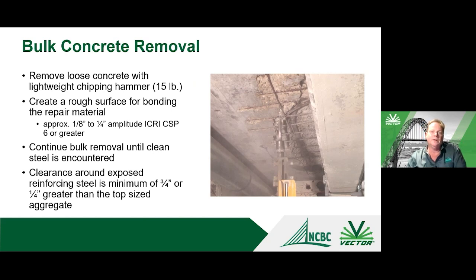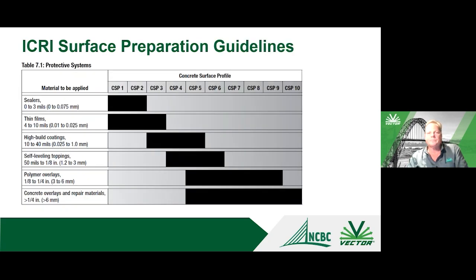of the chipping hammer can be important to remove deteriorated concrete without doing too much further damage to the base concrete or the substrate. And we want to make sure, as I mentioned before, to have a good surface profile and look at the clearance around the reinforcing steel. One good rule of thumb is if you can get a gloved hand behind the bars, that's probably going to be sufficient clearance for the repair material to completely surround.